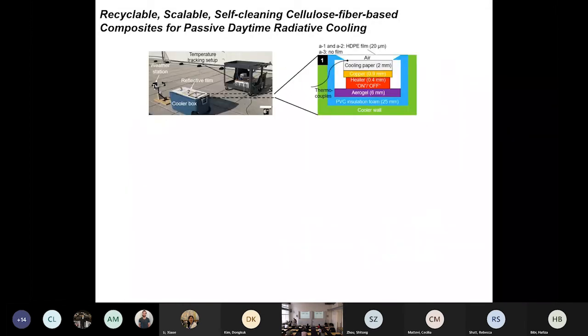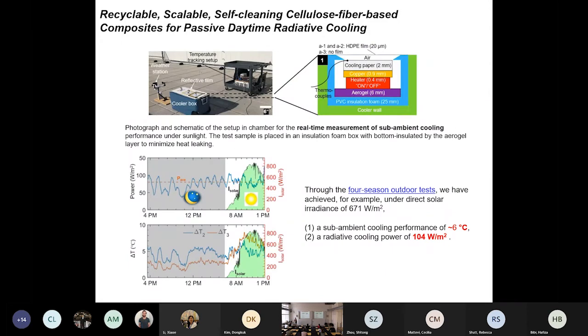But I still want to show you, we ran some outdoor tests last year in 2021, outdoors, and throughout the 4 seasons. So for the 4-season test, we ran the test almost every week, in summer and also in winter time, in Boston. On average, we're able to achieve the sub-ambient cooling performance of 6 degrees C. So what is that? 6 degrees C means we're able to achieve cooling less than the ambient temperature, the room ambient temperature, by 6 degrees without consuming any electricity.